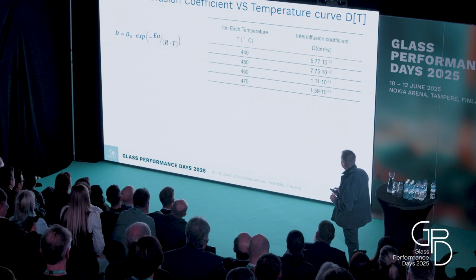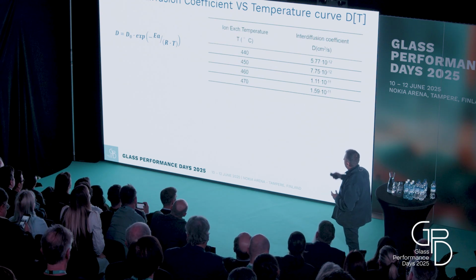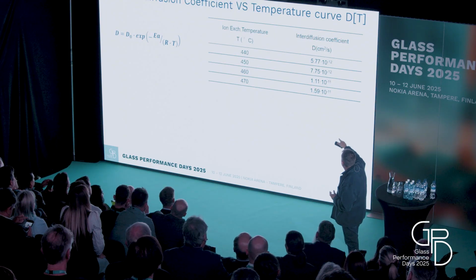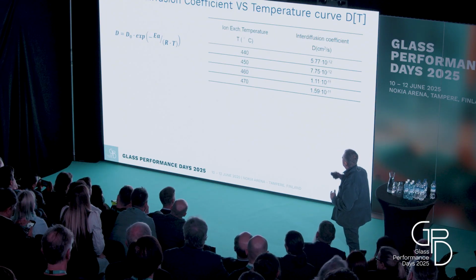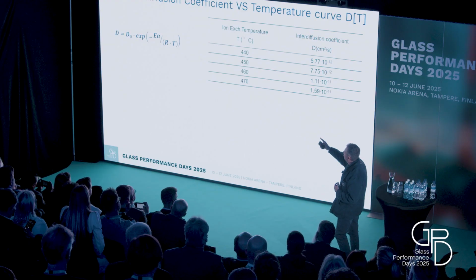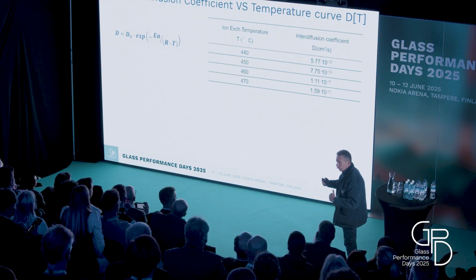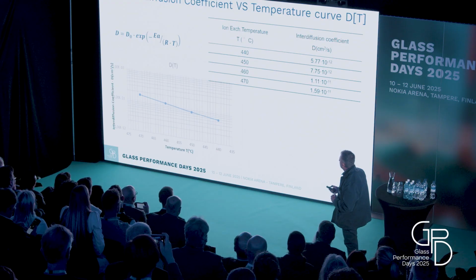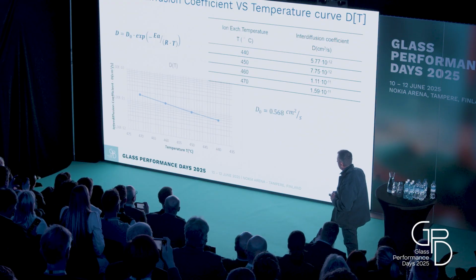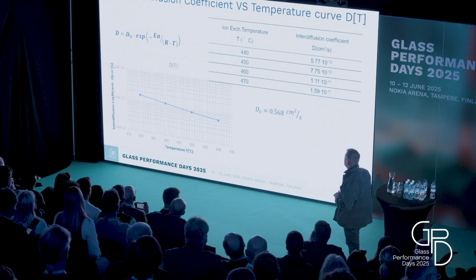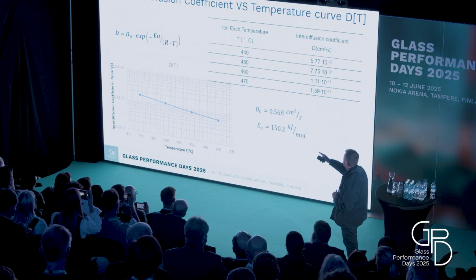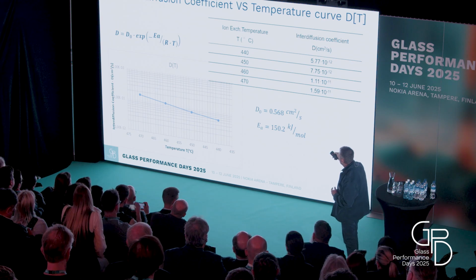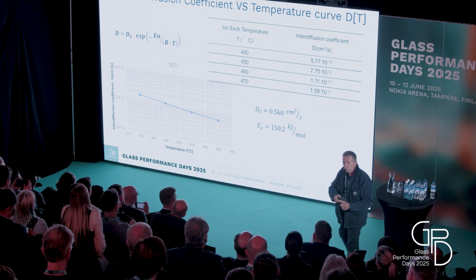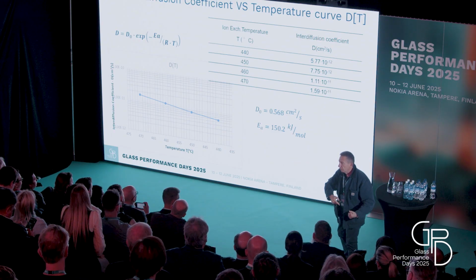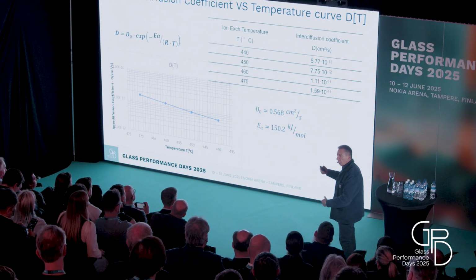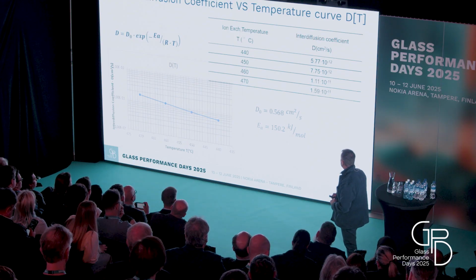The other thing you can do with this measurement, if you run the schedule at different temperatures, is evaluate the interdiffusion coefficient. You see the column on the right, and as a matter of fact, the diffusion coefficient depends on temperature through two parameters. One is the activation energy. This is a type of Arrhenius behavior. So this is put on a logarithmic scale, showing how the interdiffusion coefficient behaves. And why is this important? This is important because if you have those data, then you can make predictions for other immersion times and other temperatures of what the surface compression and the case depth can be.